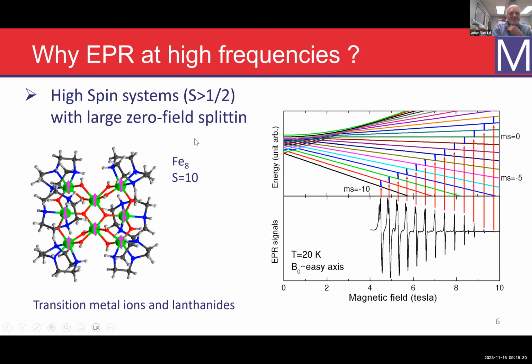So another reason is, of course, if you're looking at high spin systems with large zero field splittings, and I'll just give an example of a molecular magnet system. This is a large molecule where you have 8 iron atoms that are exchange coupled. So the spins couple together, and the total spin can end up being pretty large. And in this case, it is a spin of 10.